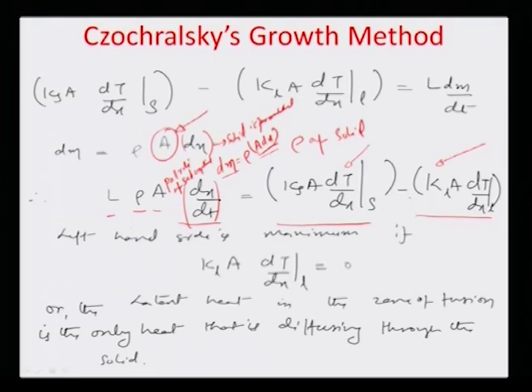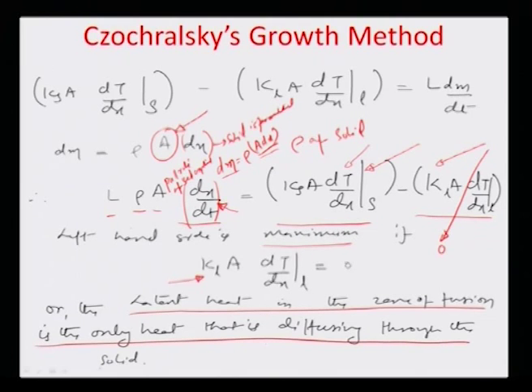So, if we assume that our pull rate is maximum for the purpose of high yield production, we should have a situation where this negative component goes to 0. Typically, whatever heat is coming into the zone of fusion is the amount of heat going away from the zone of fusion. That is the case in one dimensional heat transfer. So this whole equation is a maximum on the left side only if the heat transfer from the liquid into the zone of fusion is 0, or the latent heat in the zone of fusion is the only heat that is diffusing through the solid.